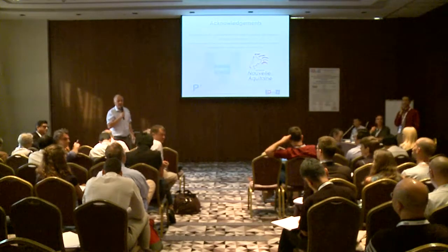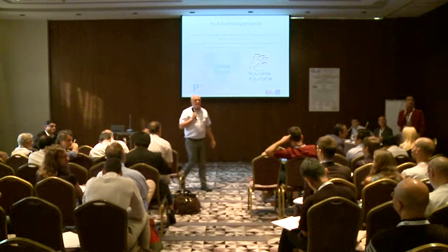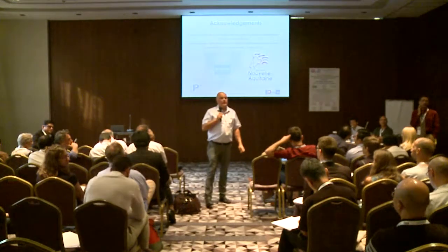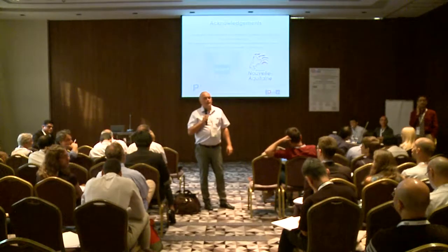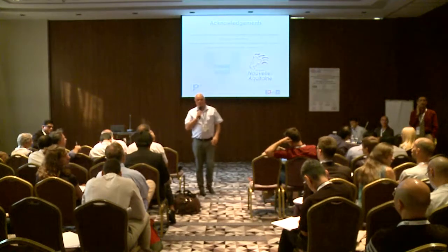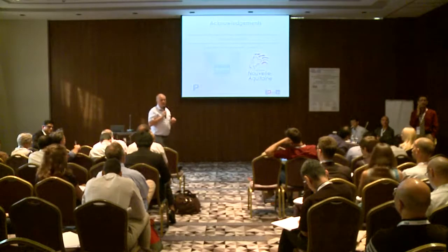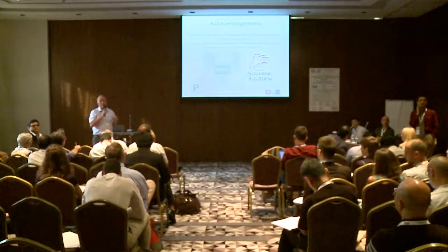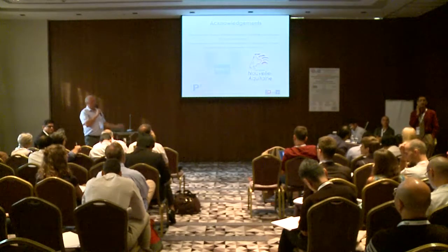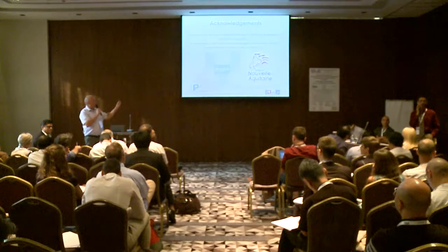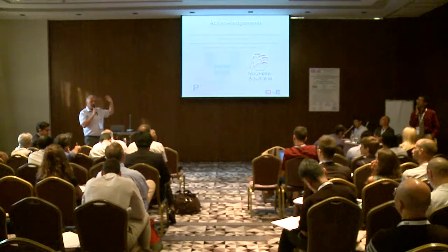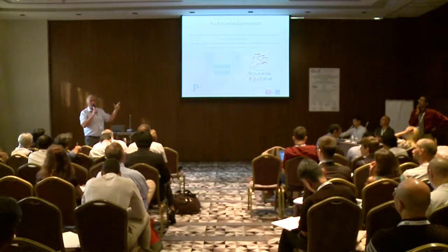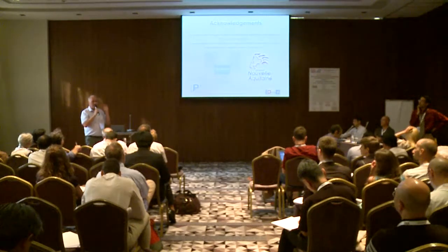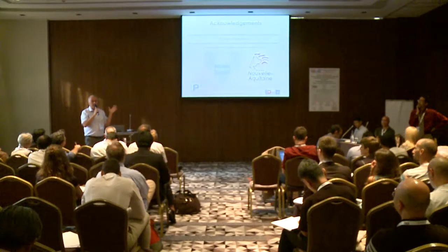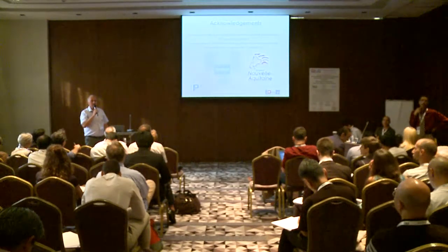But intergranular facets on relatively low strength materials is seen in fatigue in a lot of different cases, and it's got nothing to do with brittle fracture. It's not a brittle like a hydrogen fracture would be in an overload. It's not an uncommon mode. But the point is that in any other condition, in vacuum, air, or nitrogen, we never observe a single intergranular facet in this material. But it's often seen at relatively low growth rates in fatigue.